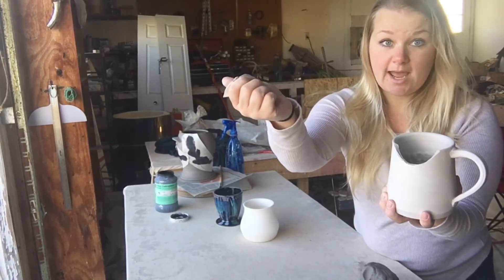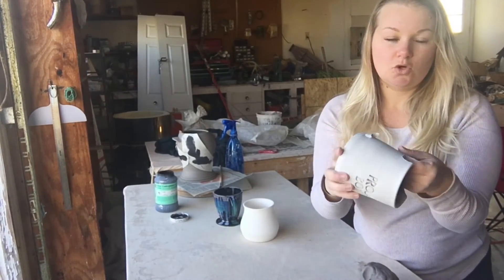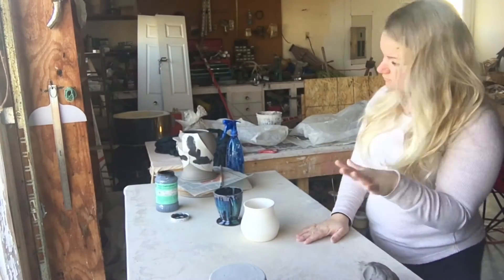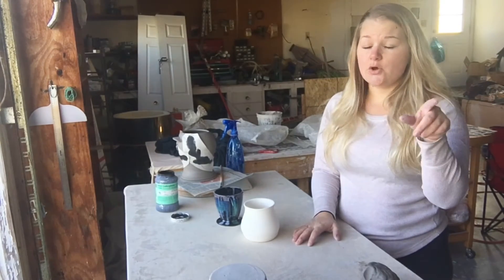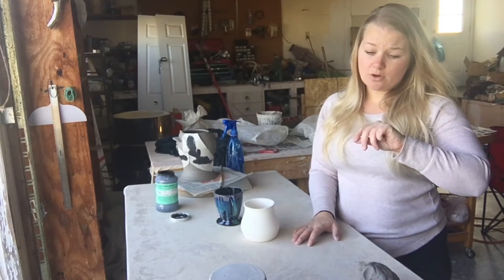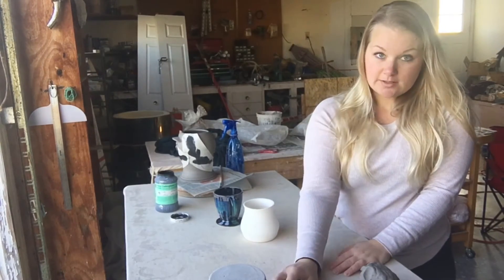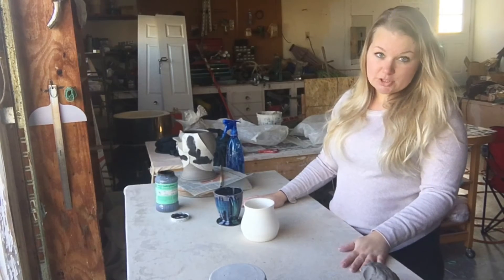I'm going to show you exactly how fragile it is when it's bone dry — you can just take it and snap it just like that, pull the handle right off. Totally brittle, dry, bad news if you're going to be rough with your pot because it'll probably break. I learned the hard way to clean up the cut on my yarn bowls because they have a spiral — I try to clean up that cut with an exacto knife when it's still leather hard, because if I try to do it when it's bone dry the spiral snaps right out of the center and it's useless.